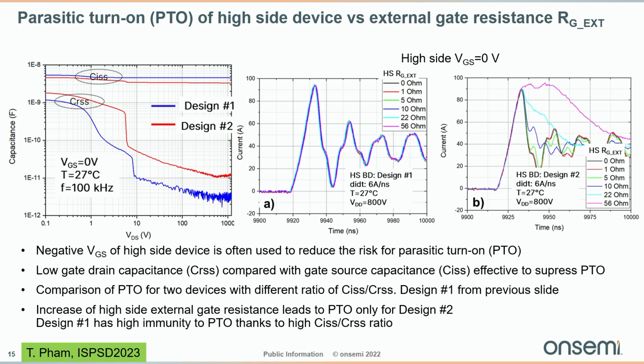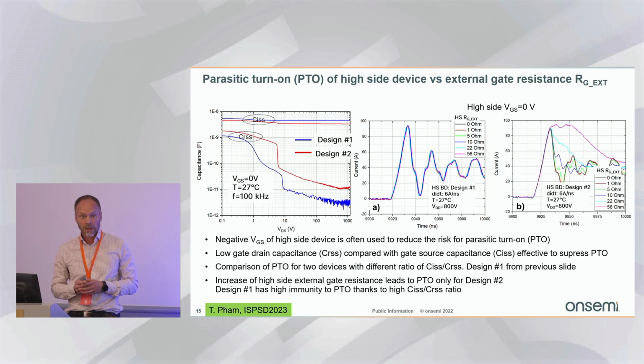Higher external gate resistance will give sensitivity to parasitic turn on. And even with 56 ohm, design 1 has no parasitic turn on. But the device to the right, which has the higher CRSS, when you go above 20 ohm, you start to see significant parasitic turn on, which is not destructive, but which increases switching losses. So the design 1 has a high immunity to parasitic turn on thanks to the high CISS to CRSS ratio.